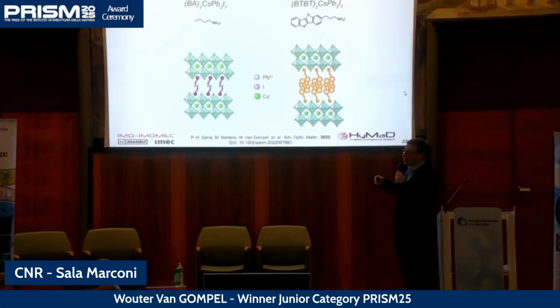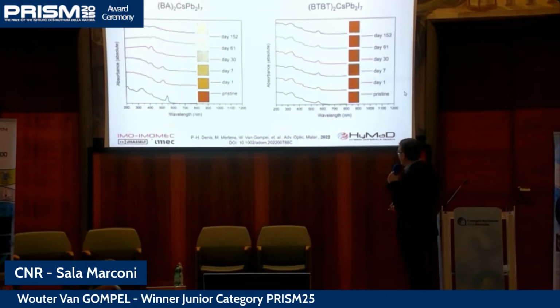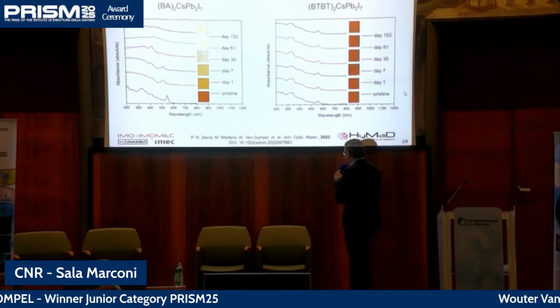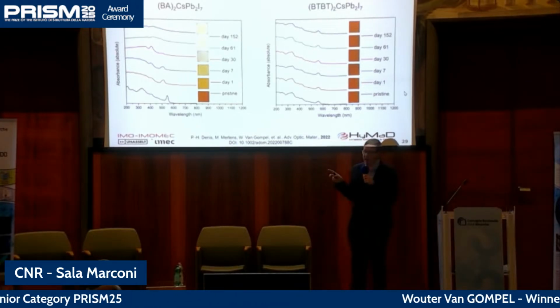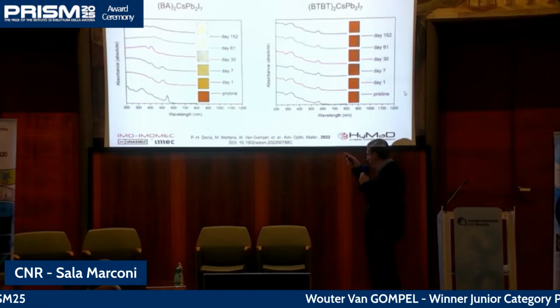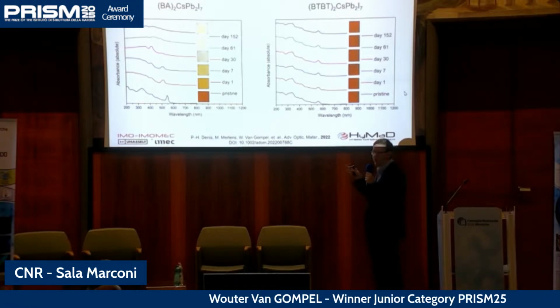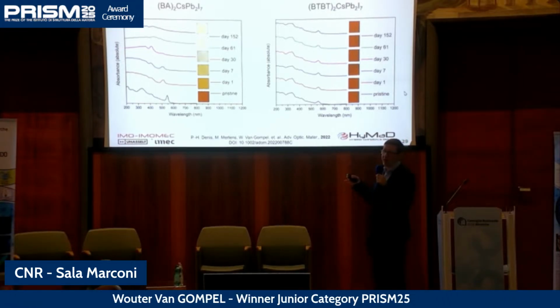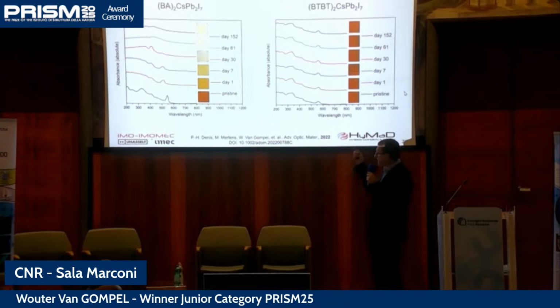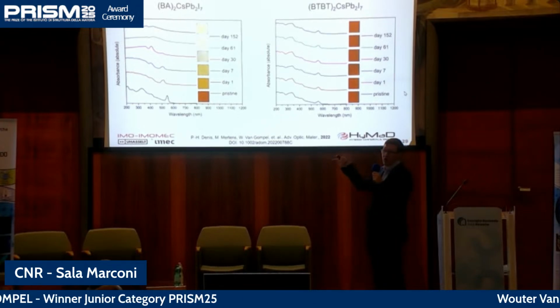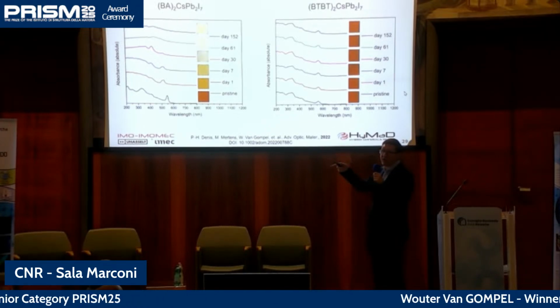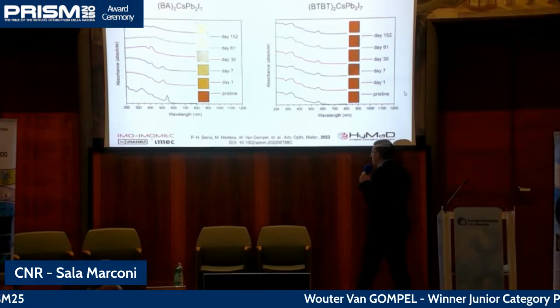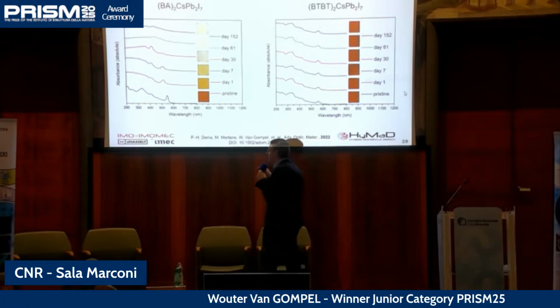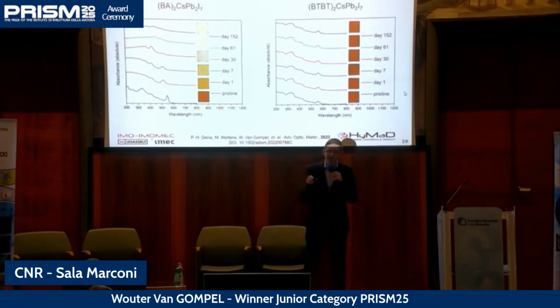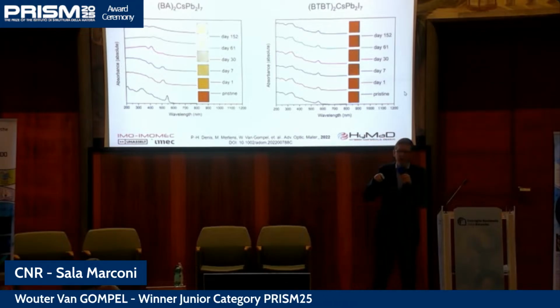Another argument is the excitonic peak position: it's at 550, and the excitonic peak position of the other one, the reference, is also around 550. If you would have a lower-dimensional one, like 1D or 0D, the excitonic peak would shift to 400 nanometers, 300 nanometers. So the fact that you have the excitonic peak at the expected position kind of proves that it is a 2D system and not a 1D or a 0D system.